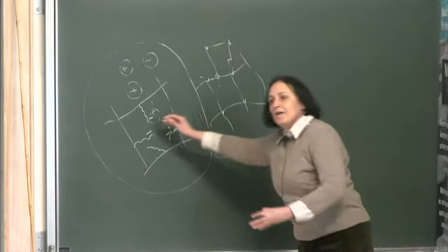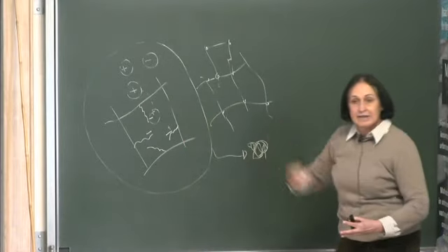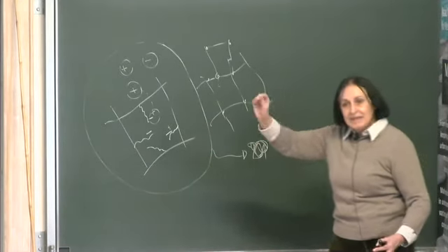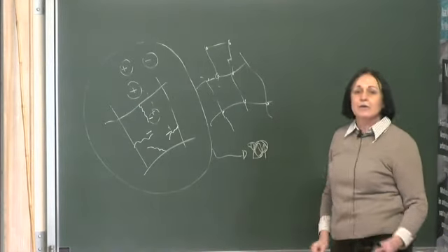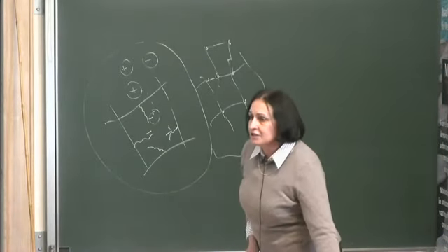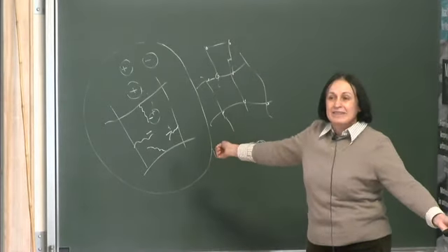They kind of remove the water, so when the network contracts, of course the water has to go away, and we have something collapsed. So this is basically, and I think it's the main idea of what goes on in the volume phase transitions that characterize these systems. So a polyelectrolyte shell can actually have volume phase transitions, where there are changes of 500 times the size, the volume. So they are huge.